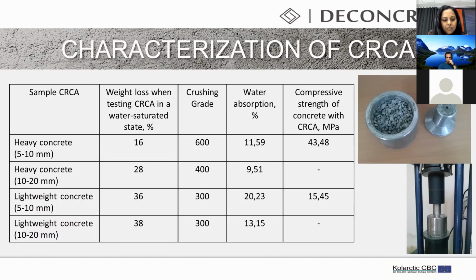We made this test, and heavy concrete with fraction 5-10 millimeters has the crushing grade 600, which is very high, and it's comparable with natural aggregates. But unfortunately, lightweight concrete is not suitable. It's only 300 crushing grade, and it's not a very good aggregate. Also, there is high water absorption for coarse lightweight aggregates.